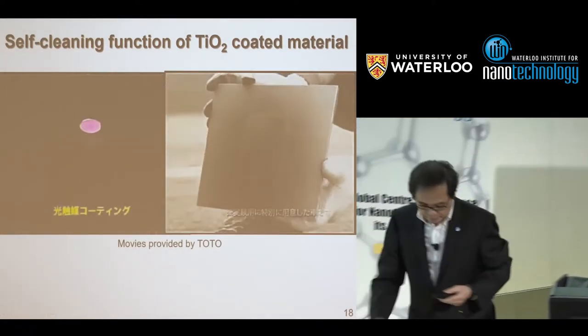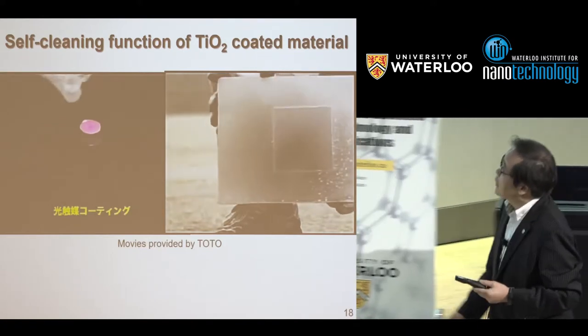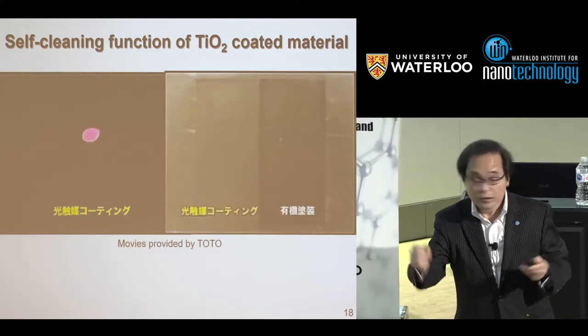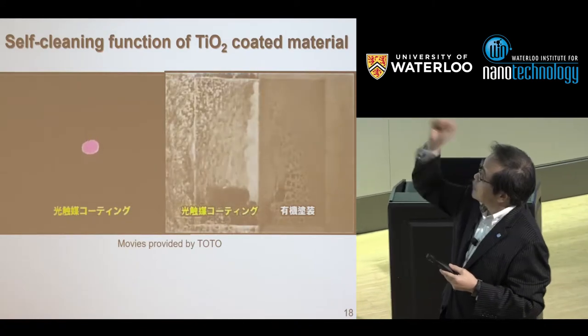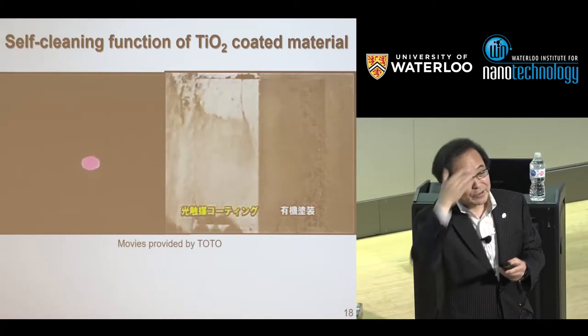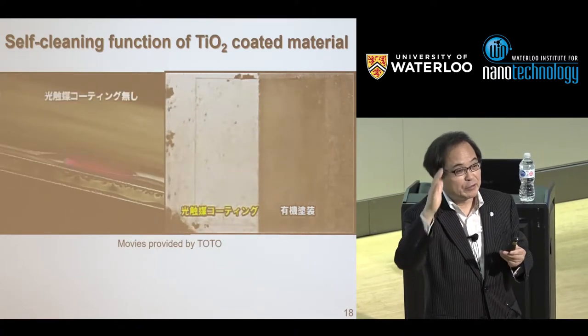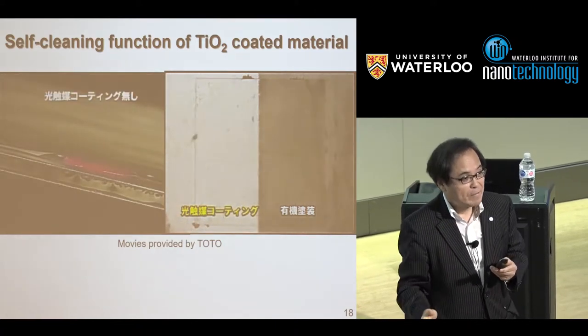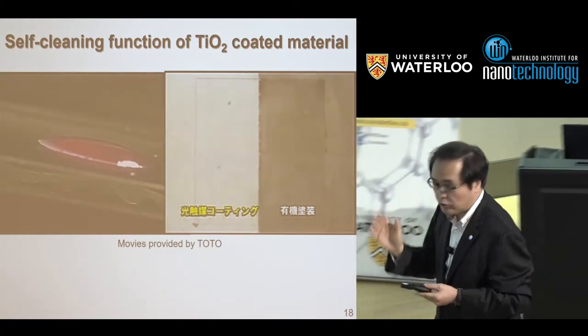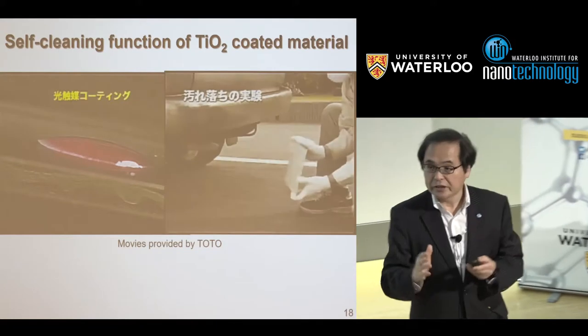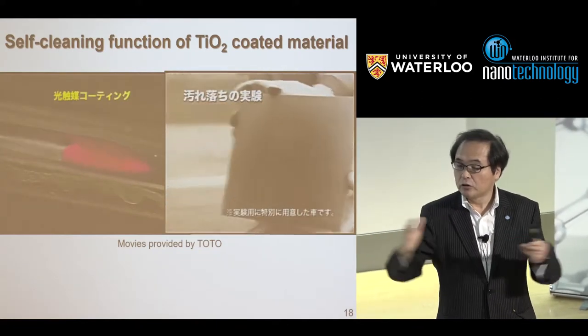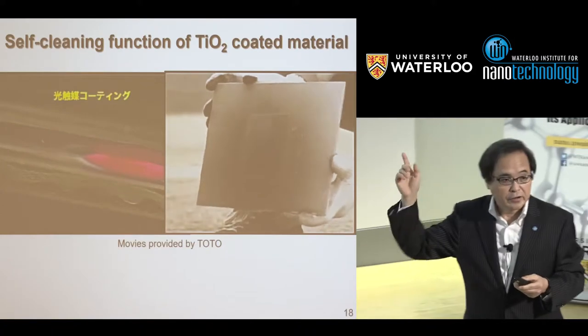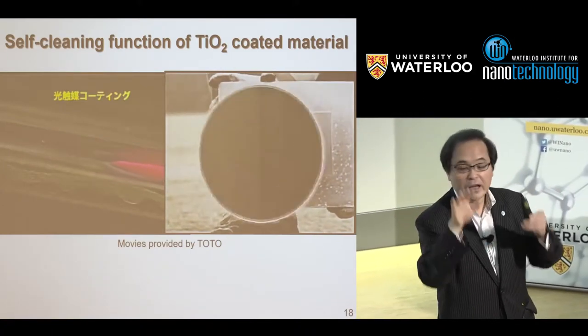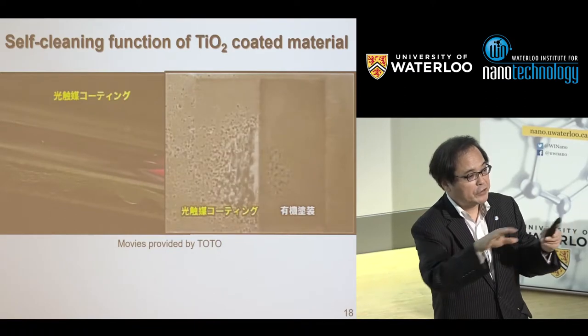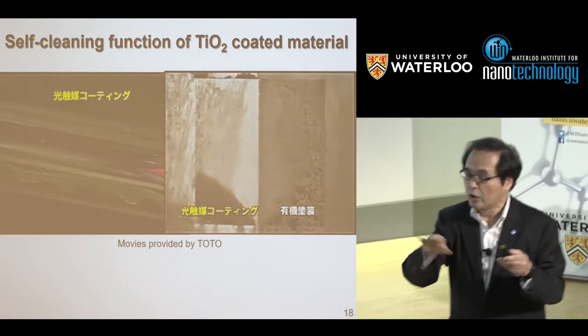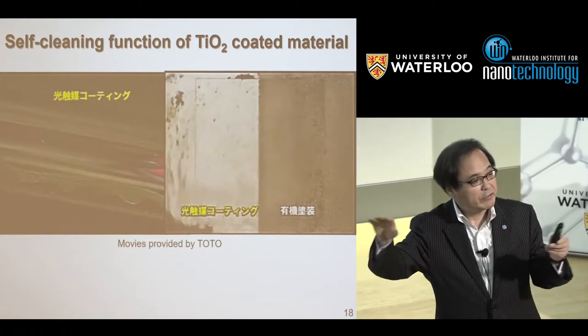The left hand side is coated with titanium dioxide and exposed to the exhaust gas. And with the water, such dirty species are easily washed out. Of course, we can decompose them by light illumination through photocatalytic reaction, but it takes time. We need a rather long illumination. But in this case, we don't need light illumination. Once it is illuminated, the highly hydrophilic state is maintained for more than several hours, or 10 hours, something like that.